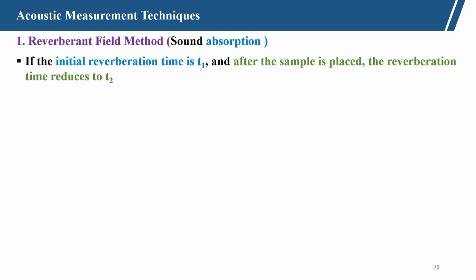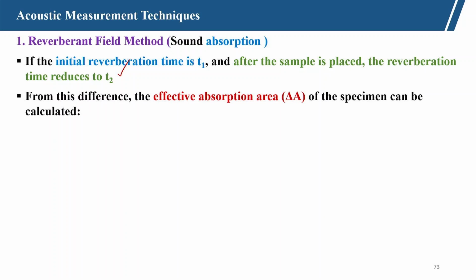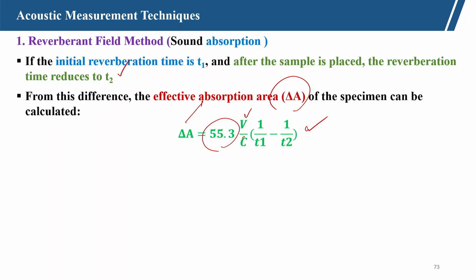And here, the initial reverberation time without the specimen is T1, and after the specimen is placed, the reverberation time is reduced to T2. Initially it was T1, then it is reduced because the material is absorbing. So, sound is actually absorbed fast, and the decibel level is reduced. So, after the material is placed, it has reduced to T2. From this difference, the effective absorption area delta A of the specimen can be calculated using the following relationship. So, effective absorption area is 55.3 V by C, times (1 by T1 minus 1 by T2).